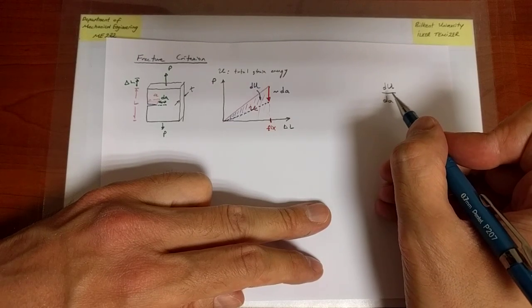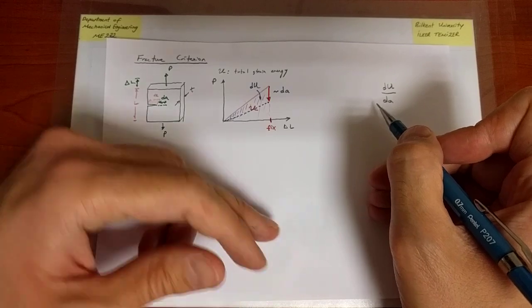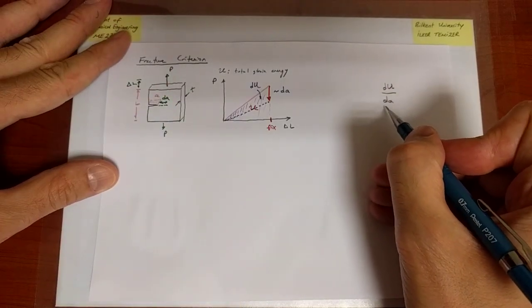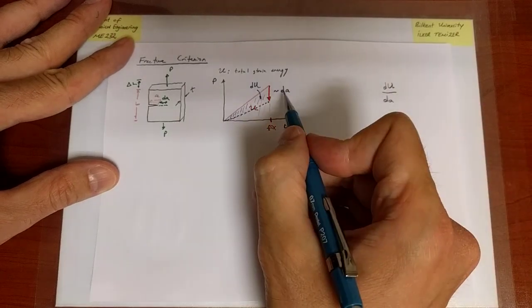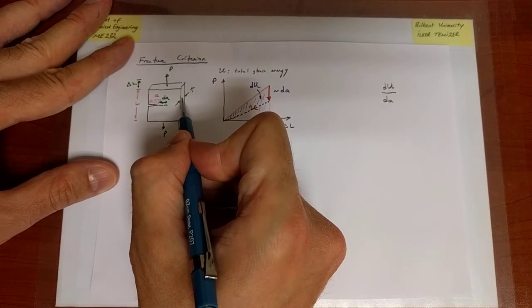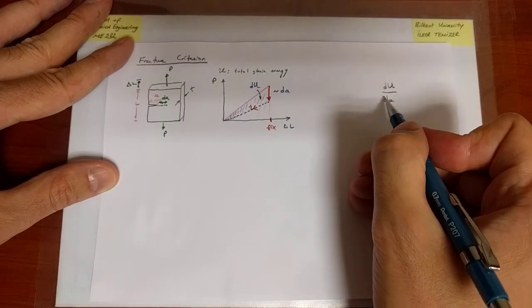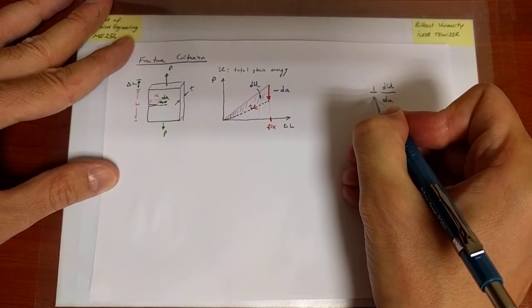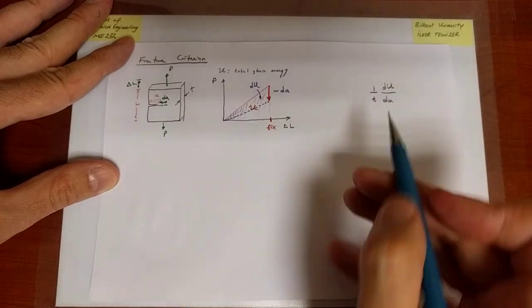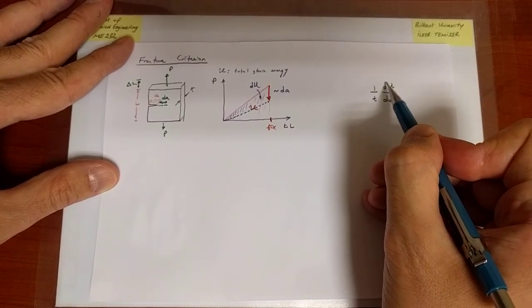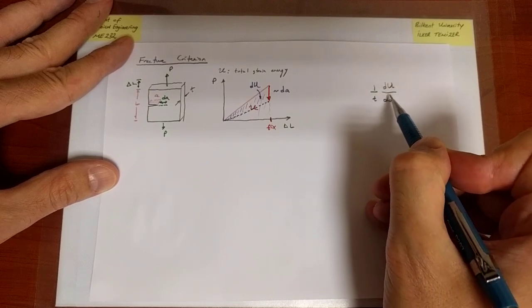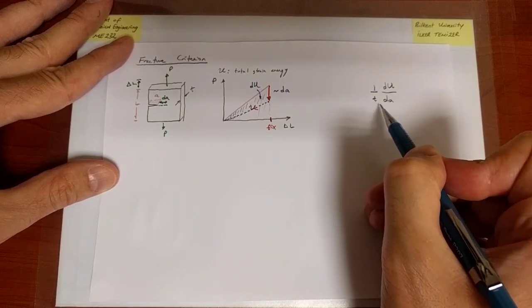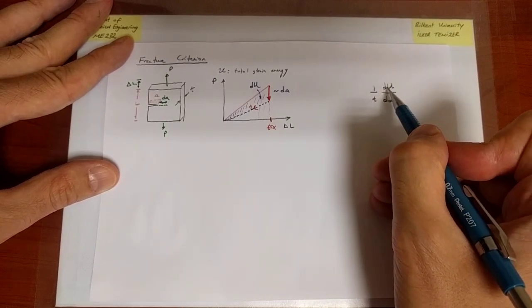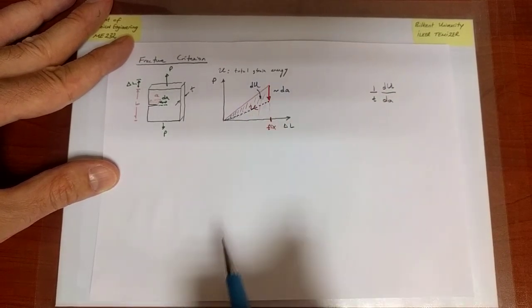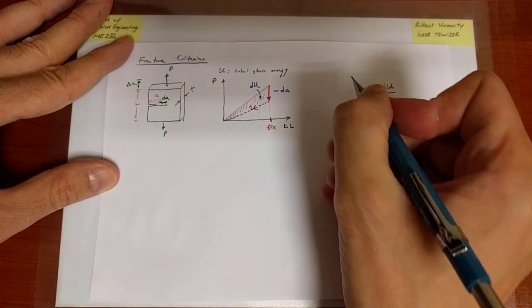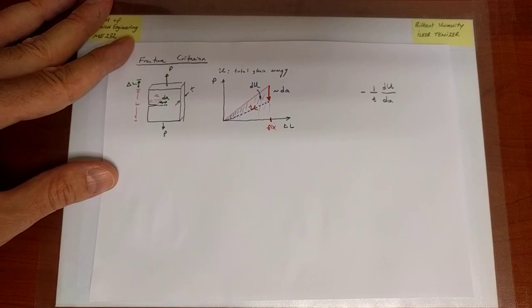So now what I'd like to do is relate the amount of energy change to the amount of new crack area that has been generated. dA is just the length of the crack. There is also the thickness, so the new area has to do with dA times T. So why don't I scale this amount of energy released by T as well, so that I see the amount of energy that has been released by unit propagation, unit increase in the crack size. Now also dU is negative because energy obviously is being released from the system. It's decreasing. To have some positive value, I am going to put a negative sign.